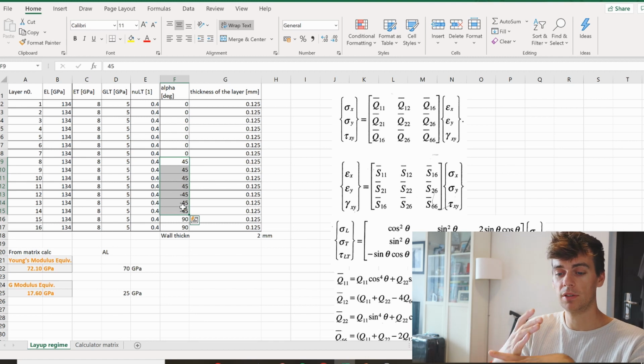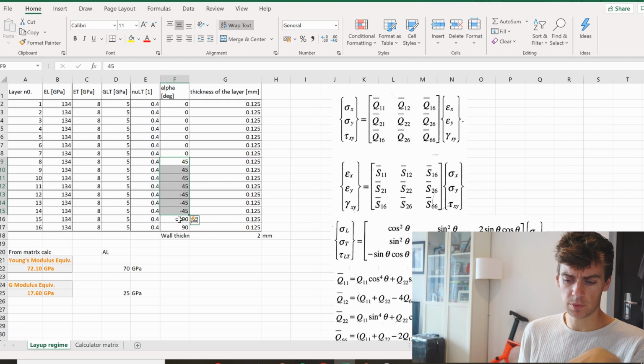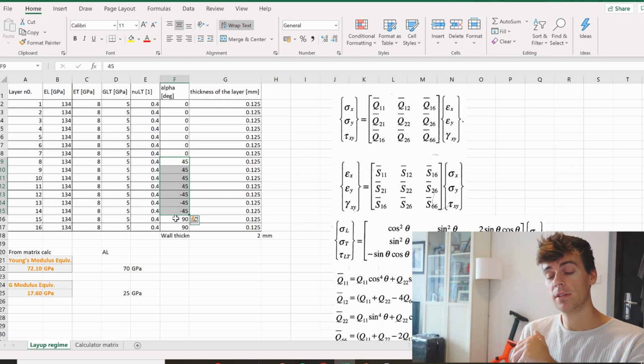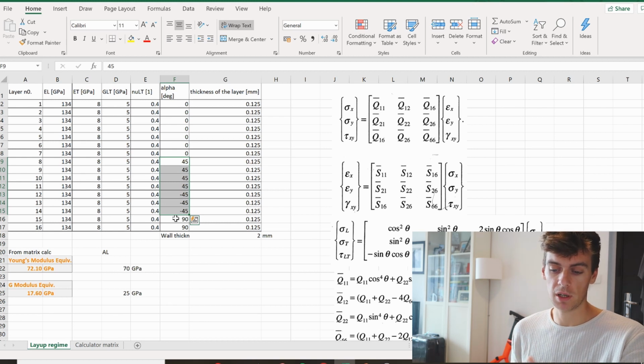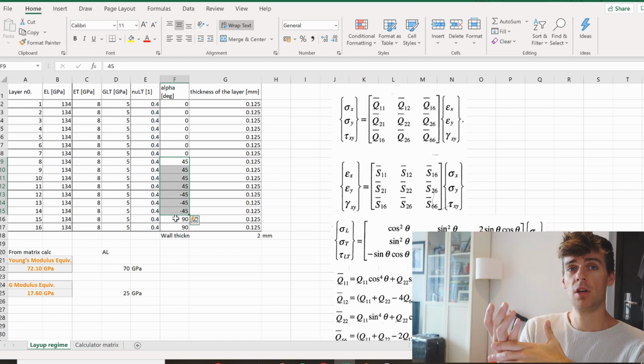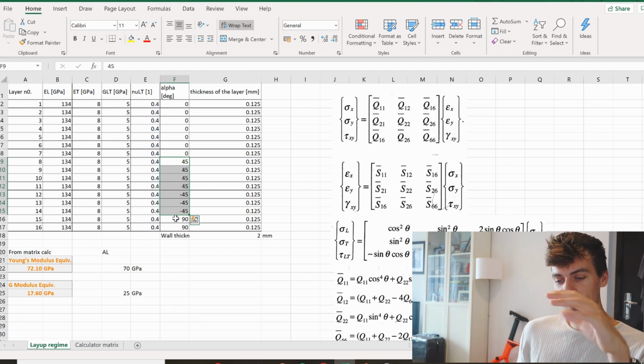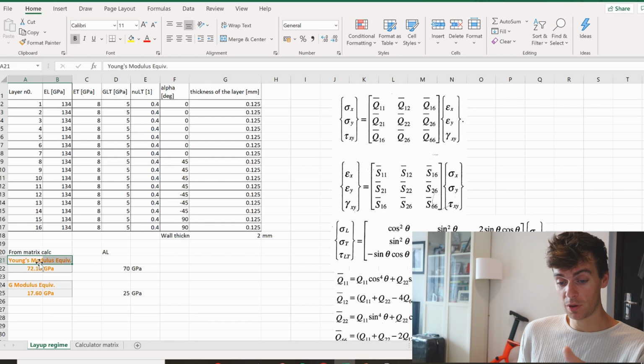The torsional stiffness comes from the pedalling and the cornering, and then you've got a couple of 90 degree layers, which can be for impact toughness or visual appearance. Sometimes you might have a 90 on top just for looks, like a woven weave. And then if you plug all these layers into the stiffness compliance matrix, we can see the equivalent Young's modulus, or the equivalent tensile modulus, is 72 gigapascals.